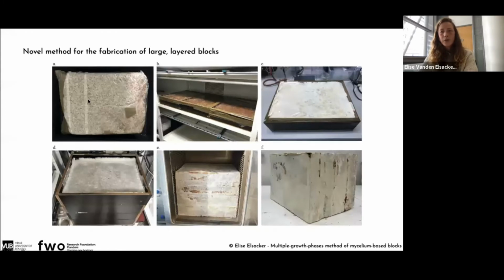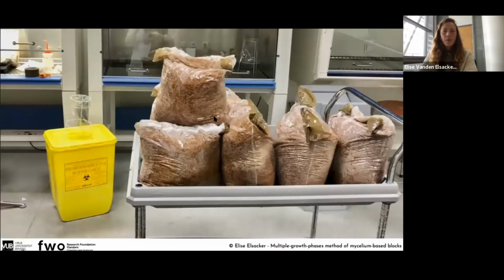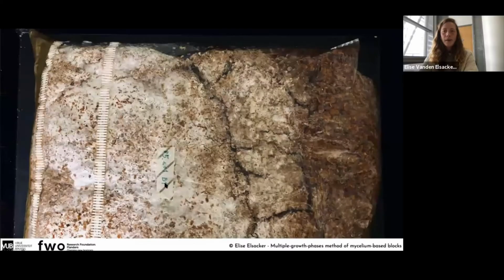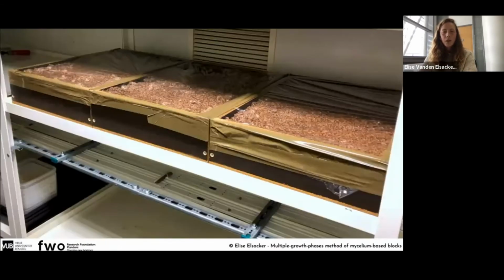During the first growth phase, the mycelium was grown in bags, as you can see here. Those bags all contain a filter system, which allowed the airflow. The mycelium homogeneously colonized the whole substrate, and almost every day I kneaded the substrate to make sure that it would distribute everywhere in the fibers, which also allowed a bit more robustness. After 8 days of growing in those bags, the substrate was crumbled by hand and distributed in those plywood molds that could be reused. Then the top of the mold was covered with breathable foil, and it was again incubated under those conditions.